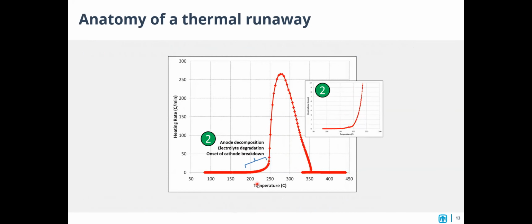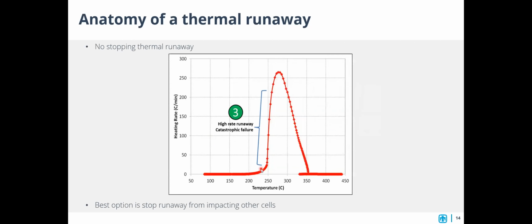Then in the higher temperature region, you actually have the breakdown of your electrodes. You want to avoid getting to this temperature range at all costs, because as soon as you start breaking down your cathode, you start to release oxygen. And oxygen, again, is needed for combustion. So even if you have your batteries in an oxygen-free environment, it can produce its own oxygen. Then you're in a state of catastrophic failure, and there's really no turning back at this point. You can't stop thermal runaway. Once you're there, it's too late.